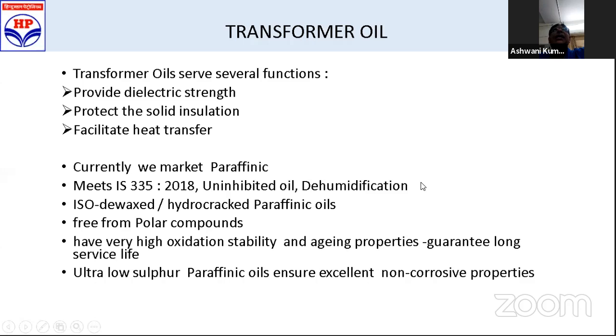But in India, whether our public sector companies or others, we mostly produce paraffinic oils meeting the IS 335 2018 version. This is uninhibited, there is no corrosion, very high oxidation stability, long life, and very low water content, almost less than 20 ppm. So it provides high breakdown voltage, so high dielectric strength, and good heat transfer rate. Top-up rates are minimal, and you get a long life of the transformer oil.